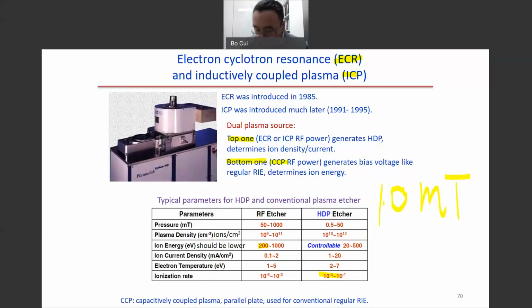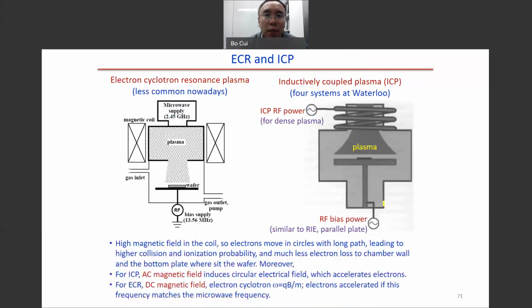Now let's look at the ECR, electron cyclotron resonance plasma, and the ICP, inductively coupled plasma, separately. First, they both use magnetic field. The difference is that for the ECR, we have the DC magnetic field. But for the ICP, we have the coil. When we have the coil, we have AC magnetic field. So that means we have this term.